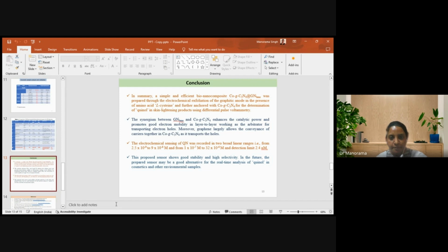So electrochemical sensing of quinol was recorded in two broad linear ranges with a detection limit of 2.4 nanomolar. The 2.4 nanomolar is the lowest concentration which can be determined through our modified electrodes. This proposed sensor shows good stability and high selectivity. So in the future, we can prepare this electrode as a sensor, a good alternative for real-time analysis of quinol in cosmetics and other environmental samples.